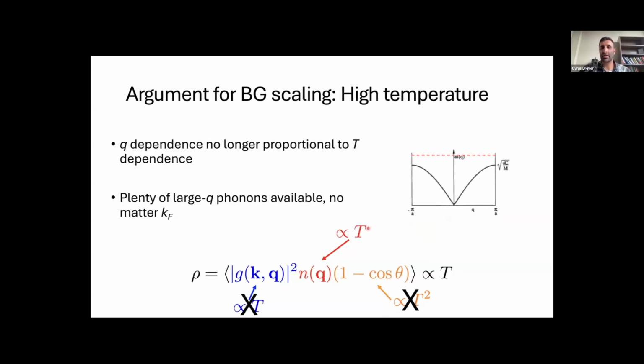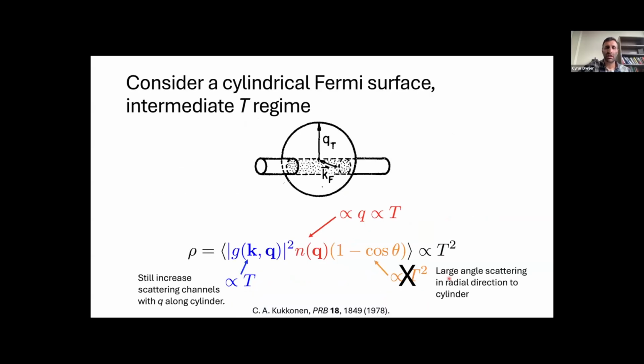Then at high temperatures, we no longer gain more Q by increasing the temperature. We lose a lot of these temperature dependencies and we get T-linear behavior. What we think is going on in these materials is that if you consider a cylindrical Fermi surface and the regime where this phonon Q is large compared to the small axis of the cylinder, but small compared to the large axis of the cylinder, then the intersection between these two shapes just geometrically depends linearly on Q, and therefore on T, at relatively low temperatures. And we also lose a little bit more temperature dependence. I won't go into the details, but it was shown in this paper that this gives you a T-squared dependence.